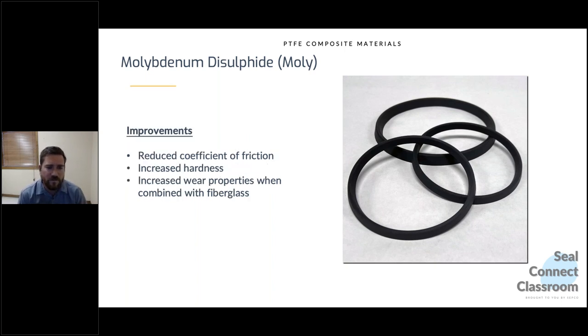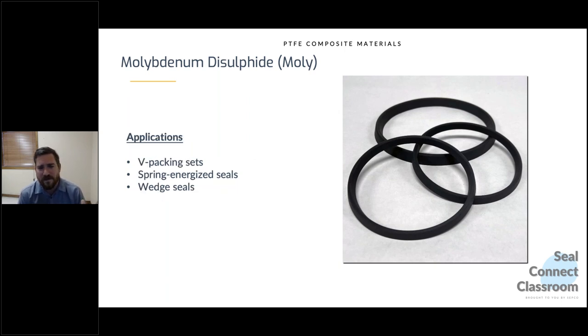So again, it improves that coefficient of friction by reducing it. Moly is very slick. It's a very slick filler. Increases those hardness, increases those wear properties when married with and combined with fiberglass. So we see primarily moly glass PTFE is used for chevron V-packing sets, spring energized seals, and even wedge seals. If y'all are familiar with the Palmetto, I think has a wedge seal, then that's fiberglass and moly because it can run well, both dry and lubricated, and it's just a great dynamic wear material.